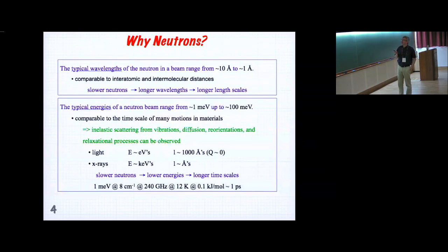With neutrons, these wavelength neutrons have meV, small meV kinds of energies. And that's the appropriate energies for many of these excitations when we were talking about spin waves and ferromagnets and so on. Whereas in X-rays, it's actually kiloelectron volts. So to probe something with millielectron volts accuracy, you have to build a very modern instrument. Some people would say getting to 1 meV is basically impossible. You have to take a beam with keV and make a resolution of meV, whereas neutrons already have the meV, and we go from there.